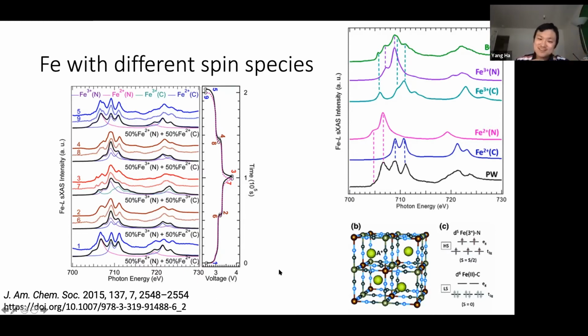So I really like this example, and I feel it should go to textbooks because it's great evidence for the Hund rule, where the low spin iron site favors the iron 2+, then you can have all the 3 t2g orbitals fully occupied. And for the high spin, it favors the oxidized form, then you can have the 5 d orbitals half occupied. So this is really cool to me.